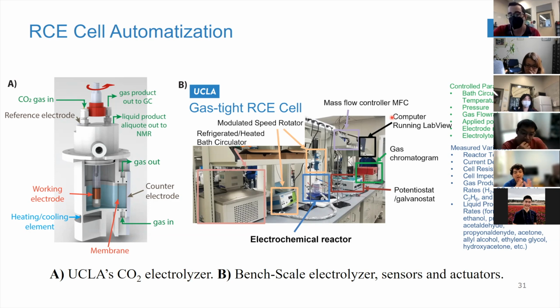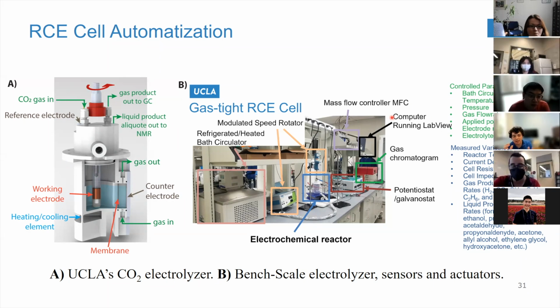So you would like to have a highly porous catalyst, right? We know that, as I showed, mass transport plays a role in selectivity. And any industrial catalyst probably will have to be porous, right? So we're now working on not only decoupling external mass transport, but also understanding mass transport inside of the pores and how that affects selectivity. And we are also working on a computational fluid, multi-scale model of the rotating cylinder electrode cell, so that we can compare what we see in the model with what we see experimentally, and we can parameterize that model. We want to capture the correct physics at the interface, with the hydrodynamics of the electrolyte and the solids, so that later we can use those same parameters to design different reactor designs, different morphologies.